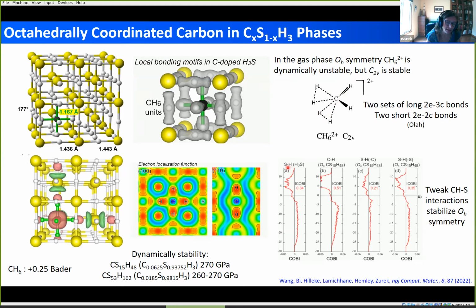What we find is that under pressure, this octahedral coordination can be found, but only at very high pressures. If you decrease the pressure, it becomes dynamically unstable, and also only for very low dopings of carbon. If you have higher carbon dopings, the octahedral environment is not favored.